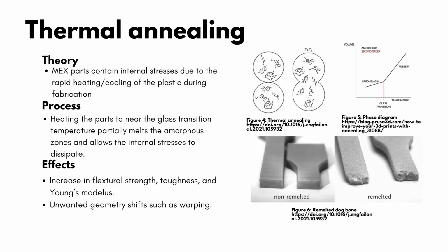Okay, on to thermal annealing. The theory is that MEX parts contain internal stresses due to the rapid heating and cooling during fabrication, and removing these stresses could increase strength. In the annealing process, parts are heated to near or above the glass transition temperature to partially melt or soften the plastic and allow the internal stresses to dissipate.